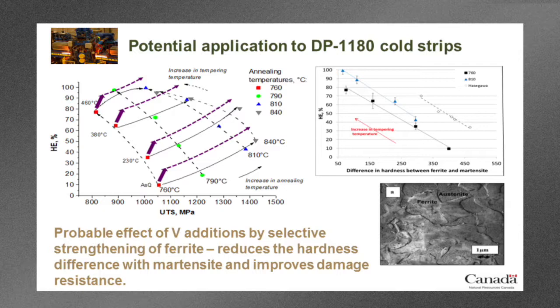And then, one of the things that's known about dual phase steels is that the damage properties actually improve as you reduce the difference in hardness or in strength between the two constituent phases, between the martensite and the ferrite. That's shown on this experimental graph here on the right. Plotted along this axis is the difference in hardness between the martensite and the ferrite phase, and up here is the measured hole expansion coefficient, and you can see you get a strong improvement as you reduce the difference. And that's quite logical. We're reducing the strain partitioning, we're reducing the damage formation.